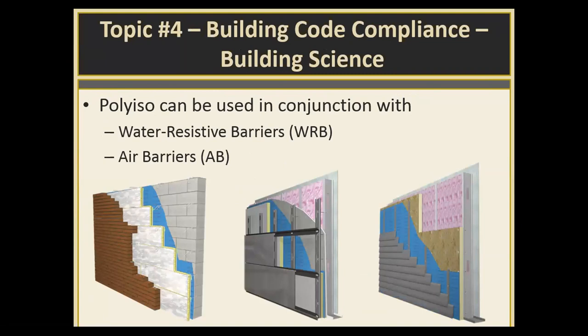Polyiso can and is often used in conjunction with separate water-resistant barriers or air barriers, and those barriers can go on the backside up against the base wall or on the top side of the foam insulation. Either which way is being done throughout the country. A lot of the building scientists are recommending putting it on the top side or the exterior side of the insulation. That allows you to see penetrations that are being made in the water-resistant barrier or air barrier, as opposed to it being behind the insulation where any penetrations, you can't see the holes that are being made. You can at least see them and fix them if it's on the exterior side.